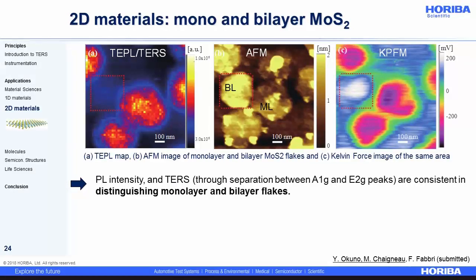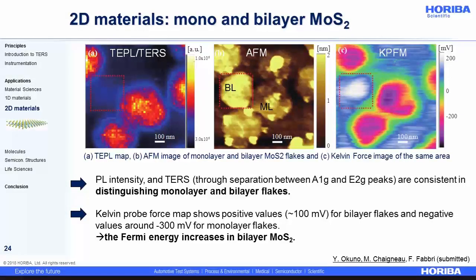Then you can see a clear difference between the tip-enhanced photoluminescence map and the AFM image in that the bilayer, annotated BL in the AFM image figure B, completely disappeared from the tip-enhanced photoluminescence image figure A. And this is consistent with the observation in the previous slide. Finally, the change in the optoelectronic behavior revealed by this tip-enhanced photoluminescence map can be linked to the electronic properties through the surface potential variation that we see in figure C. One can see that the Kelvin probe map shows positive values for bilayer flakes and negative values for monolayer flakes. So we have a Fermi energy that is increasing in the bilayer molybdenum disulfide flake.